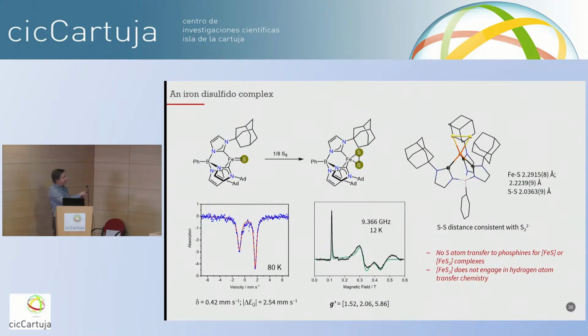And this actually does react with more sulfur. So if you add more sulfur, you get a disulfido complex here, which is now a spin 3/2. Again, from the EPR, the g tensors are most consistent with 3/2. It's a square pyramidal geometry. And what's surprising, I think, is that this compound doesn't seem to transfer sulfur atoms to substrates such as phosphines, and it doesn't do any other really interesting chemistry.